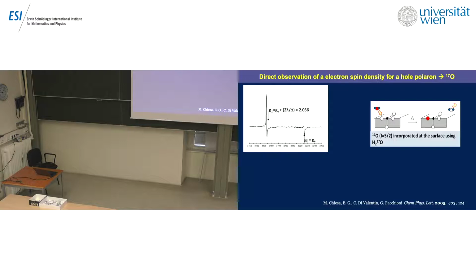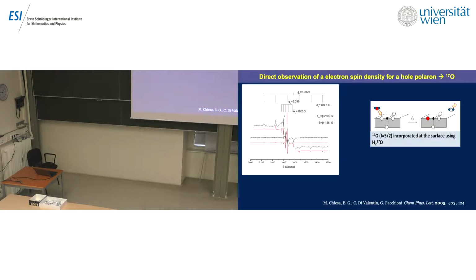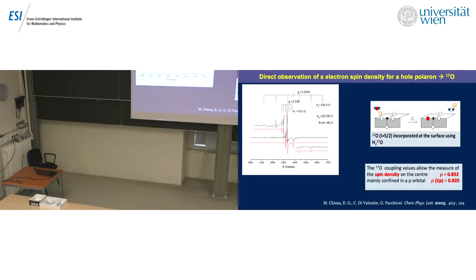And so we incorporated at the surface, using water, oxygen-17, and the same experiment produced another spectrum with exciting information, that is the hyperfine due to oxygen-17. From this value of hyperfine separation, you can go back to the contribution of the various orbitals, and what you find is that the spin density on the center is about 83%, and is essentially based on a contribution of a 2p orbital, dipolar contribution. The s contribution is practically negligible, it is some spin polarization, something that is not important to compute, and this was published in the past. Just to see one case in which we were lucky to determine anything.